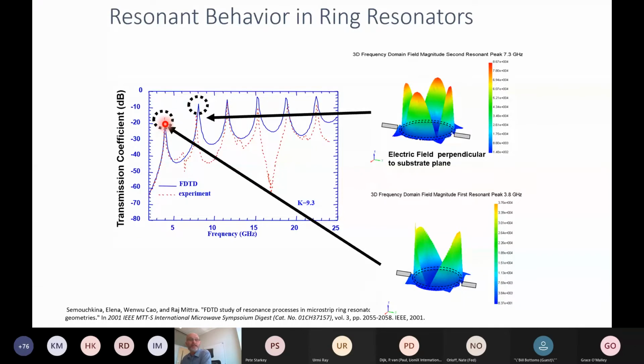So these are basically harmonic frequencies of some sort of integer number of wavelengths running around the circumference of this ring. These are some very early simulations that we did, some finite difference time domain, some homegrown code to actually just model the electric fields in this case. And you can see this basically representation of the different harmonics shown here, where we basically have one wavelength as we run around this ring. And you can see here at the second harmonic, you basically have two wavelengths running around this ring. So you can see the data. We're basically plotting that transmission coefficient versus frequency. We'll focus mostly on just the fundamental mode at this point.